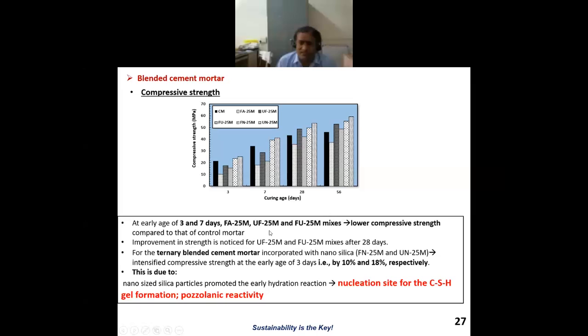So there was a lower compressive strength in the early ages, that is 3 days and 7 days. Now come to the ternary blended cement mortar. The moment you go for the ternary blended cement mortar, that is fly ash nanosilica 25 percentage, ultrafine fly ash nanosilica 25 percentage, you can see even the early age strength at 3 days increased by 10 percentage and 18 percentage respectively. Now that is the advantage actually. The moment you add, even though a very small percentage of nanosilica, you remember we have added only 2 percentage of nanoparticles and 23 percentage of secondary cementitious materials, still this very small percentage could increase the early age strength significantly.